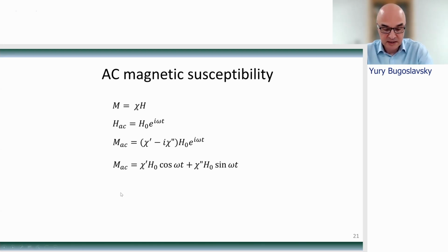Alternatively, this result can be written as a sum of two components, like in this bottom line here. One component is proportional to cosine omega t, so this becomes what we call in phase with the magnetic field, and the sine component comes at 90-degree shift to the applied magnetic field. The coefficients in front of these terms, chi prime and chi double prime, are usually called real part of susceptibility and imaginary part of susceptibility for obvious mathematical reasons. In physics, of course, they both describe very real phenomena.